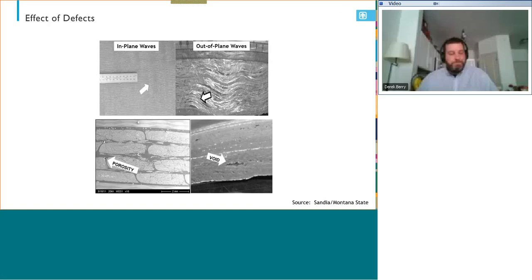These look similar to what the previous speaker talked about. I wanted to point out that a few of these are actual real pictures from wind blades. We can have in-plane and out-of-plane waves. We can have porosity. We can have voids, which are sort of a bigger porosity, or maybe interchangeable in some cases. But all of these have a different impact on strength and fatigue. Some may present themselves very quickly. Some may take a long time to have damage grow from them. And so it's really important, I believe, to do these tests not just with perfect materials, but with actual materials that you find from your process.